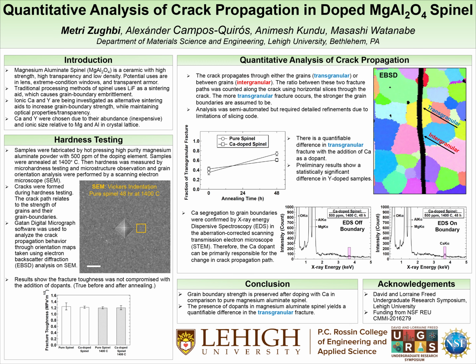Now, this sounds great, but the process is only semi-automated due to limitations with the code and software. The code can't differentiate between colors, like seen on the picture on the right, so they have to be converted to grayscale, which means complementary colors can show up as the same shade of gray. In addition, there are things like pores, which are these random black dots, and scratches that make it more difficult for the code to get things correct, so there are copious amounts of spot checking that I have to do.